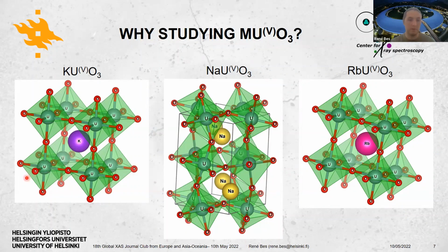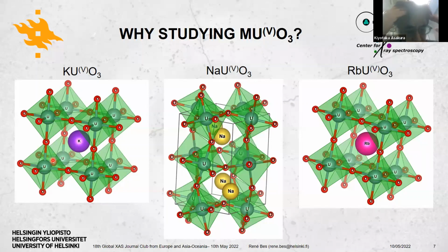there is a kind of alignment which is expected if you consider those octahedra in X, Y, and Z. But if you consider the other orbitals, which are more complex, like the D and F, you may have orbitals pointing somehow in the diagonal, meaning that there should be less interaction or bonding between oxygen and uranium using these orbitals, if they are not well aligned with this. So therefore, the oxygen P is split by the directions. Should be, yes. It's the most important. In that case, it's almost the perfect case in the sense that they are well aligned in the right direction. Okay, thank you very much.